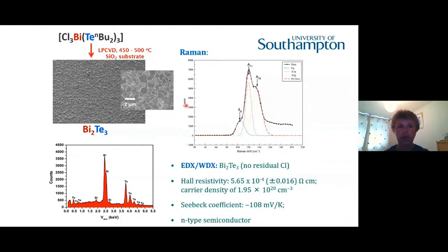And you can see from the scanning electron micrographs here that we actually do see very nice coverage of Bi2Te3. This is polycrystalline material. We can see that coverage is very nice, and we've got what looks like quite highly oriented material. This is a rhombohedral structure, so these are hexagonal platelets or rhombohedral platelets which are lying flat down on the surface of the substrate. We can track the characterization using Raman spectroscopy, and this is a characteristic Raman spectrum